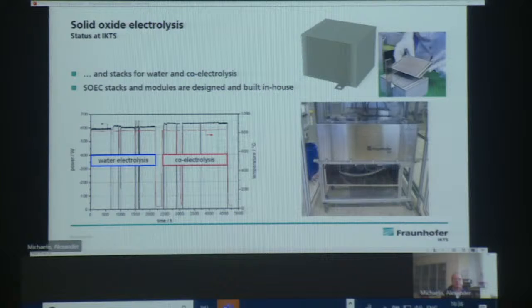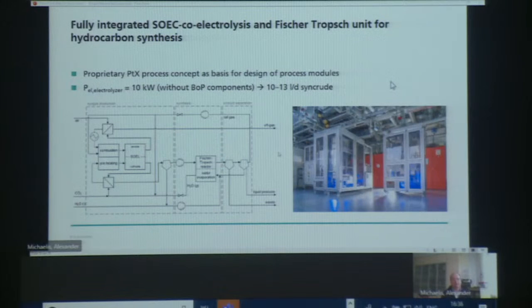You see also that you can use this. Here's again a long-term test is shown, 5,000 hours. The operation was switched from pure water electrolysis to co-electrolysis here, which is easily doable. Again, you see almost no degradation in these stacks, so it's working very well. Here a 1 kilowatt stack is shown. Here you see our 20 kilowatt stacks by modularizing these stacks. So very important technology. And we then combined this technology to a very complex system, and we are very proud on this.